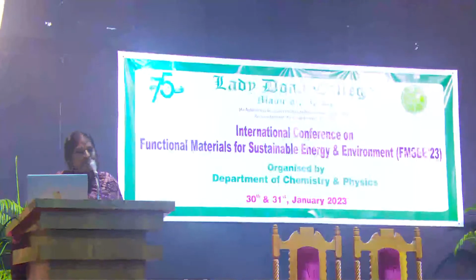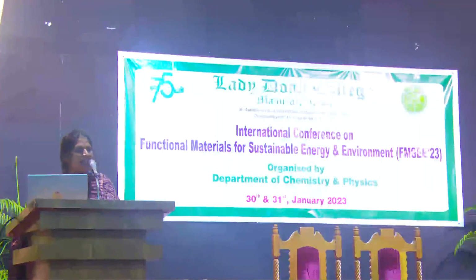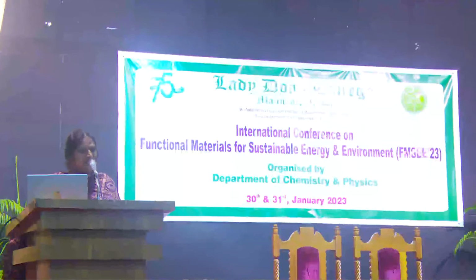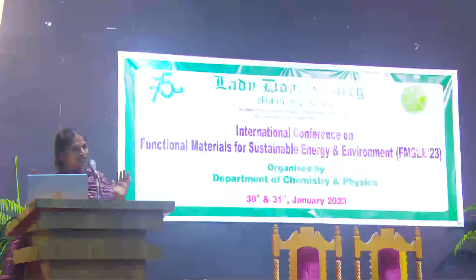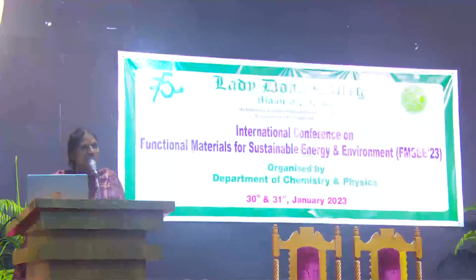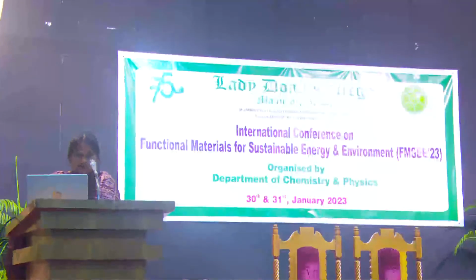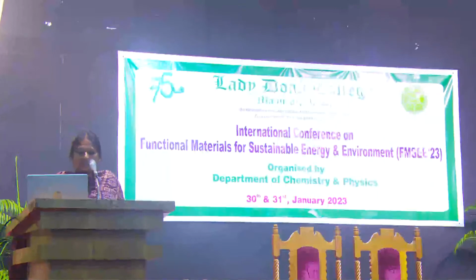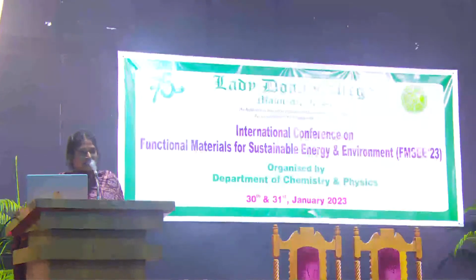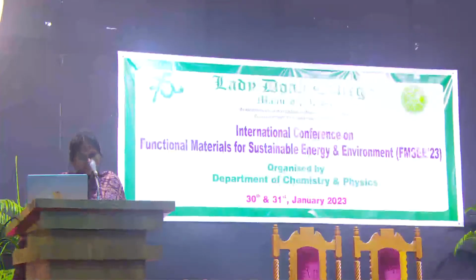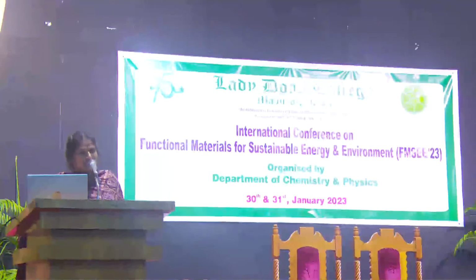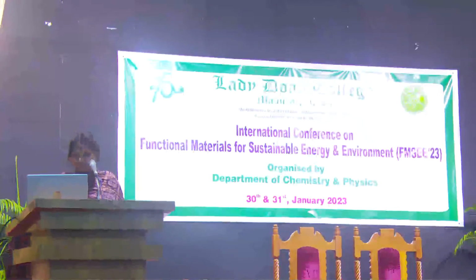And the final application part: CV confirms the leaf-like structure. This exhibits the EDLC behavior of the sample, and no oxidation reduction hump is noted. From that we can confirm that the charged ions are stored at the surface of the electrode, not at the interstitial sites of the electrode. And the discharge capacity is 1860 at the 30th cycle. After the 33rd cycle, it decreased to 1500, then it retains the same discharge capacity. So this capacity relies only on morphology and voids.